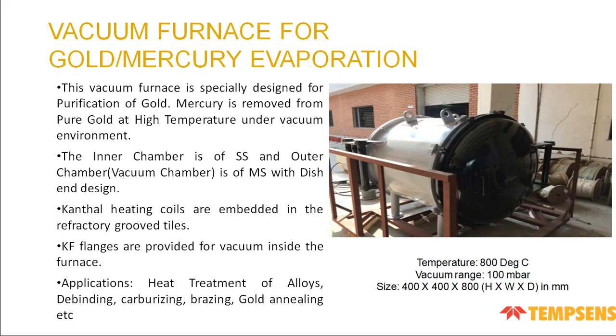And we have used an inner chamber of SS and outer chamber of MS with dish end design. Kanthal heating elements are embedded in refractory grooved tiles, and flanges are provided for vacuum inside the furnace. The vacuum of the furnace is around 100 millibar, and the size is 400 by 400 by 800. So this type of furnace can be used in heat treatment of alloys, debinding, carburizing, brazing, gold annealing, etc.